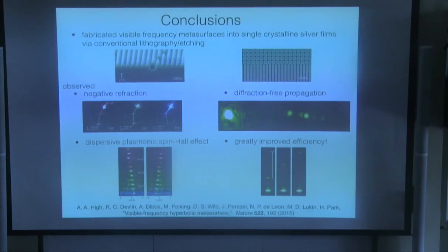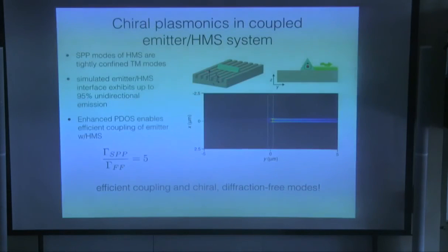Generally, the more sub-wavelength, the more you go into a metasurface regime, the better. Right, more pronounced. Yes, so for instance, these simulations are for a metasurface with 150 nanometer pitch. All of these coupling effects, all of these advantages from having this hyperbolic dispersion, are related to how small of a device we can fabricate.